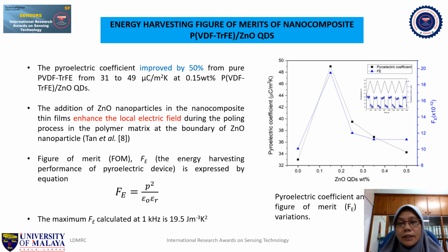Energy harvesting performance of this polymer nanocomposite is analyzed by obtaining the figure of merit as shown in this equation here. So the figure of merit is obtained from the pyroelectric coefficient, P squared divided by epsilon naught, epsilon r. In this figure, it indicates that when we increase the composition of zinc oxide quantum dots to 0.15 weight%, the pyroelectric coefficient and figure of merit increase tremendously, which is about 50% improvement compared with the pure VDF-TrFE, from 31 to 49 microcoulomb per meter squared Kelvin. However, as the composition is increased above 0.15 weight%, the figure of merit and pyroelectric coefficient are reduced tremendously.